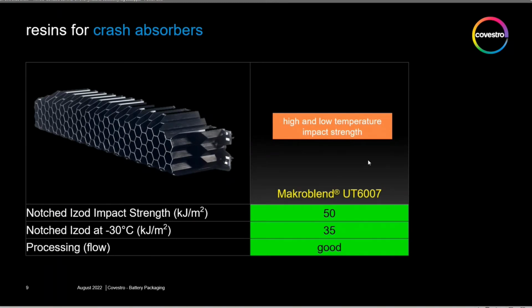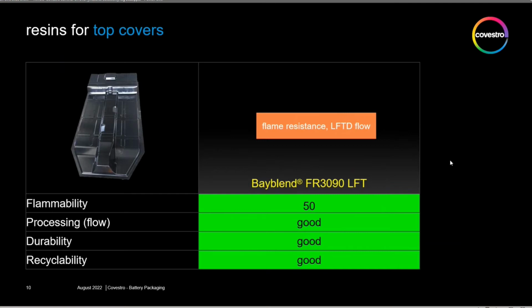So for crash absorbers, our recommendation for this material is really the best part of our portfolio for impact resistance. And that material is Makroblend UT6007. This is a blend of polycarbonate and PBT, and it offers superior impact strength at both high and low temperatures. So for crash absorbers, this is our go-to material.